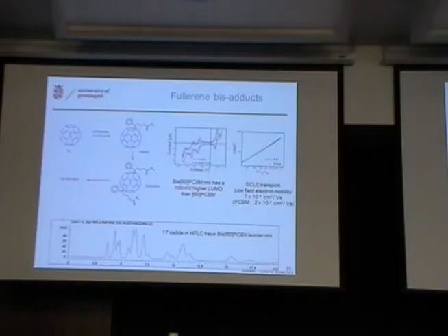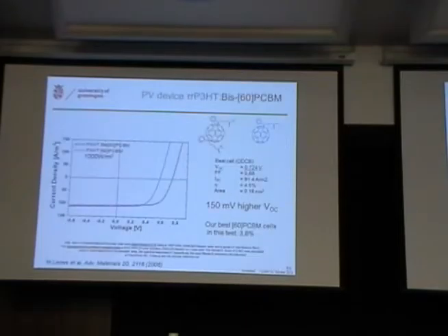But does this transport? How does it go? Well, this is the plot of space charge limited current determination of the mobility, and it's funny, the mobility in this case is roughly 7 times 10⁻⁴ centimeters squared per volt second, which is only a factor of, let's say, 3 less than PCBM. So for the fact that you have such a horrible mixture, I think it's surprising that it's still working.